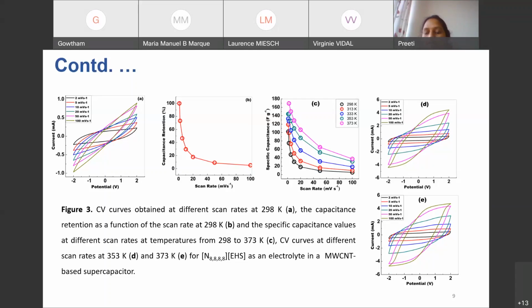which is very good and gives another feature to this ionic liquid, because most ionic liquids or electrolytes cannot be used over a very wide range of temperature. But this ionic liquid can be used from room temperature up to 100 degrees centigrade, or maybe we can go further beyond, but there were some limitations with the instrument temperature, so we haven't done that.